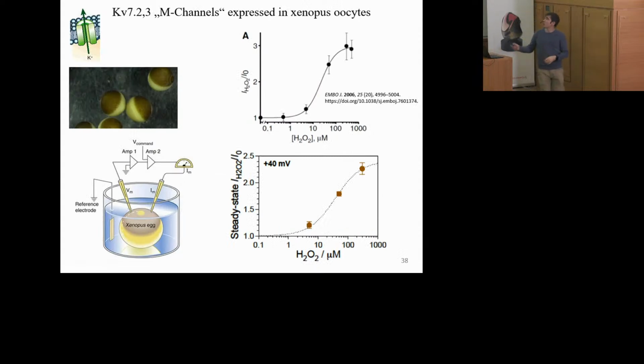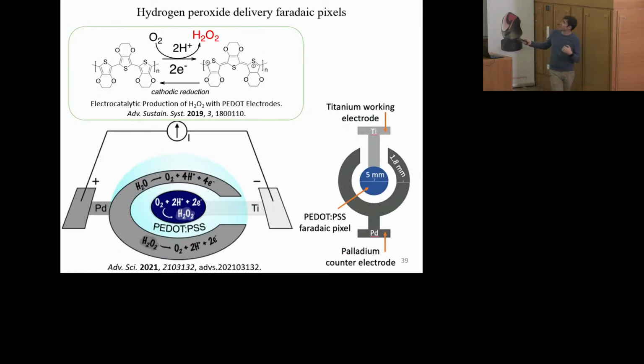So what we did is we used our favorite model, Xenopus oocytes, to overexpress these channels from this 2006 paper. And we tested that if we add peroxide, we get a very similar response curve to what Nikita Gamper published in 2006. And then what we did is we developed a pixel, which is going to use this organic technology that was the DREAM. So we used the organic catalyst from the DREAM in order to create an electrode that's going to specifically dose the peroxide to this single cell. And around that electrode, we're going to put a guard electrode, which is going to neutralize that peroxide. So we have like a peroxide fountain, which can stimulate individual cells.